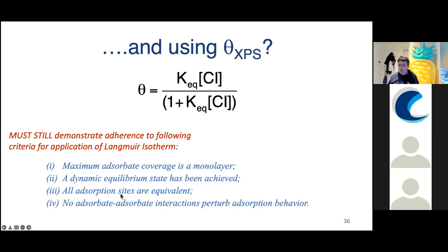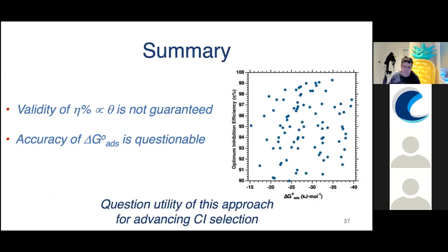But more importantly, all adsorption sites are meant to be equivalent. That's unlikely because on a very rough surface, we're going to have steps and terrace sites. So all these sites are going to be quite different. And also, you cannot have any adsorbate-adsorbate interactions when they're adsorbing on the surface, when they're forming an overlayer on the surface. If these criteria are not met, you cannot apply this equation, this Langmuir isotherm. And essentially, when people are doing this, no one is checking whether this works, even for the XPS. I cannot really say whether we fit these criteria in our work. So I would be very dubious about using this, even if you had XPS.